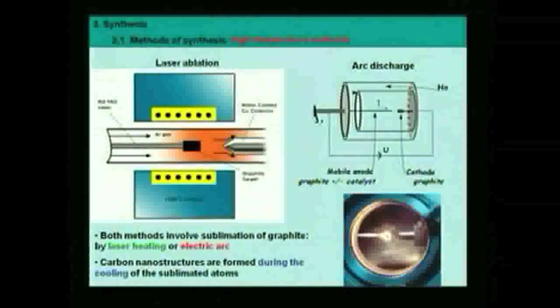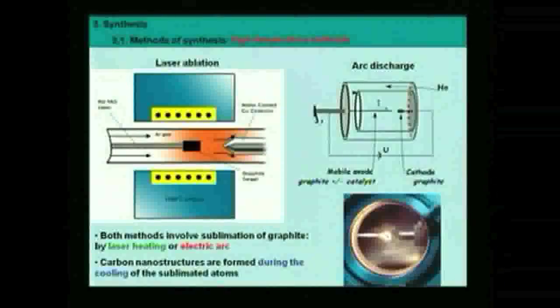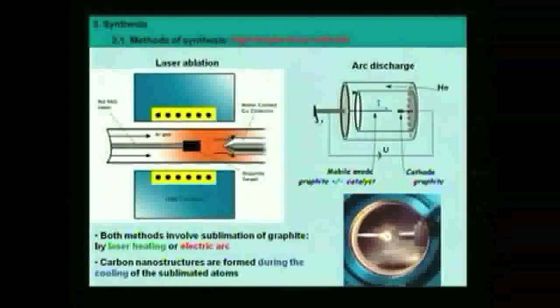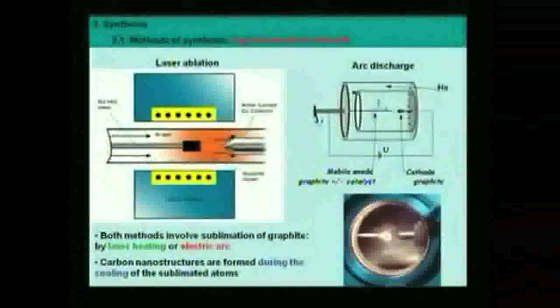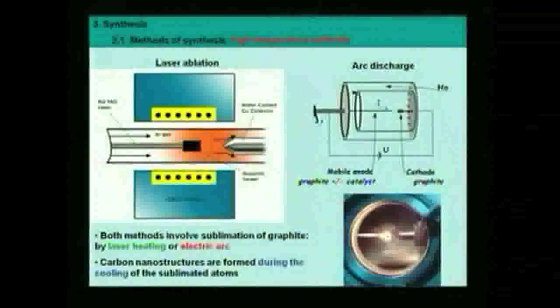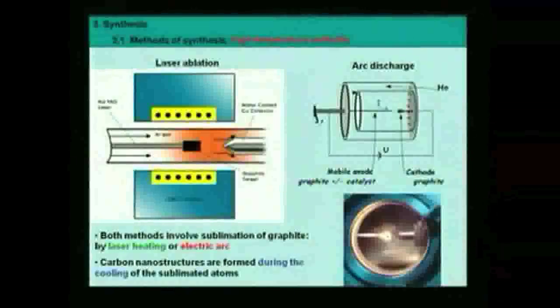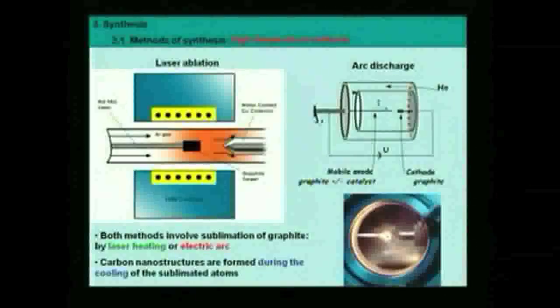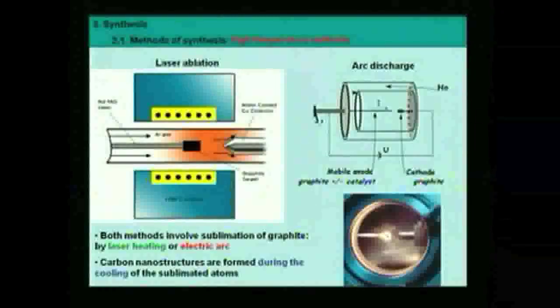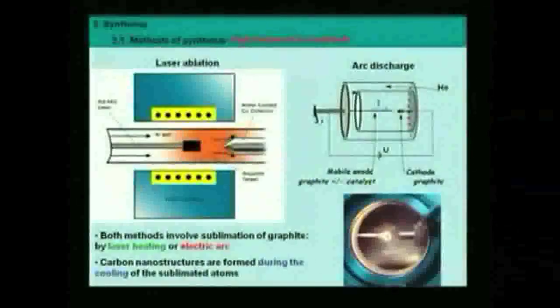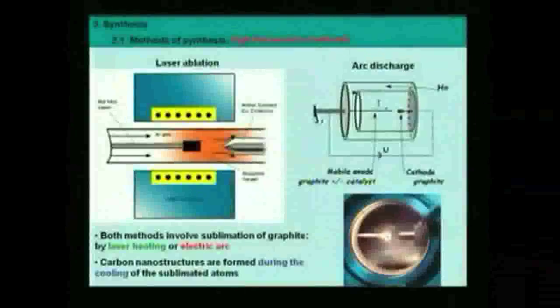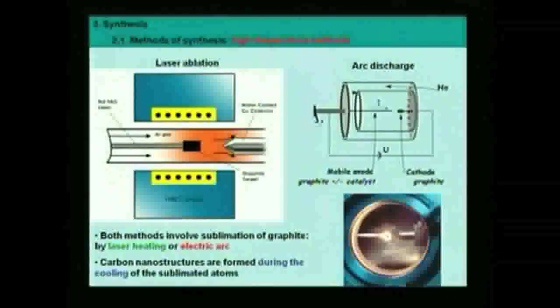To keep the distance constant between the two electrodes, because there is a consumption of one electrode, you need to have a mobile electrode. This is why you push the anode toward the cathode all along the synthesis in order to keep the gap constant, to keep the electric arc. Because if you have a too large gap, you will lose the electric arc and you will stop the plasma. Then you will have cooling of carbon atoms. In this technique, there is no water-cooled collector, but very often there is like a tubular form around the central part where carbon structures will deposit, and then you can collect them at the end.